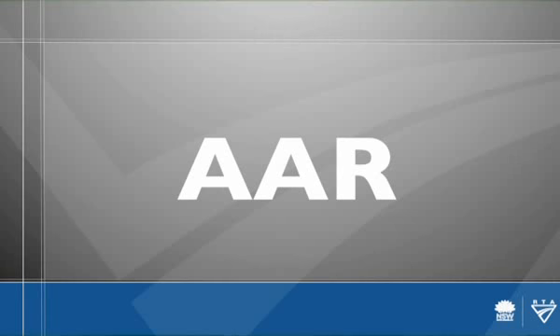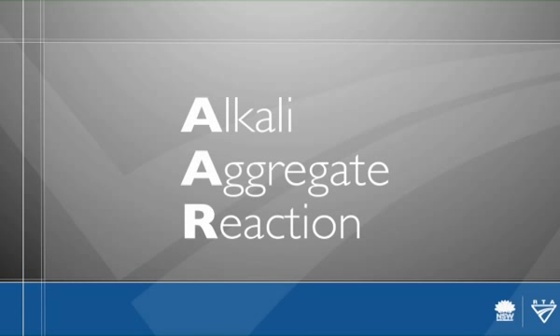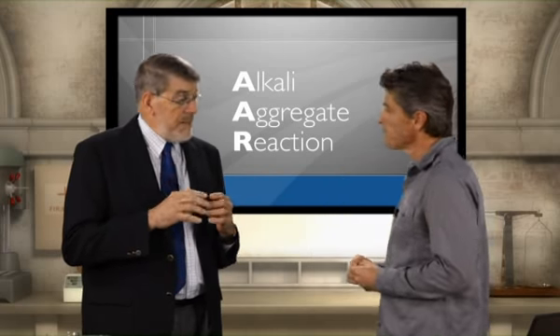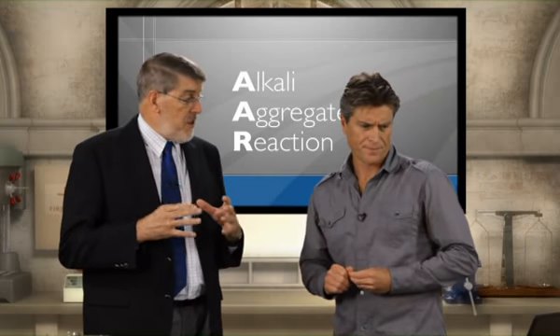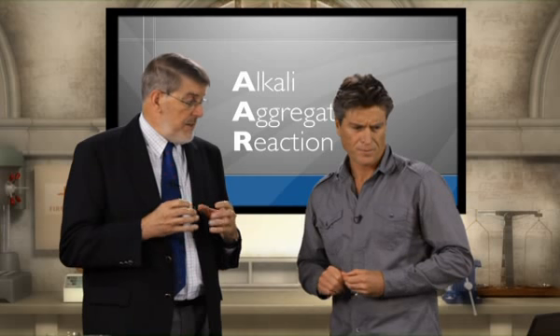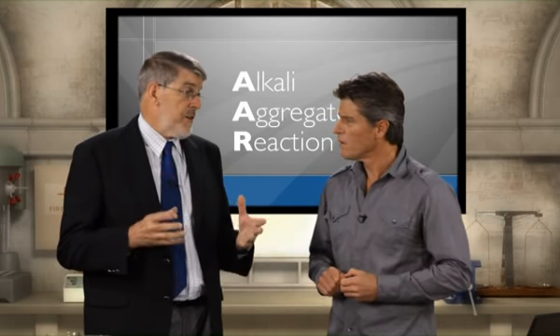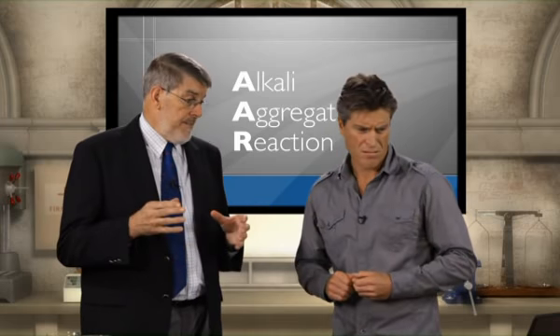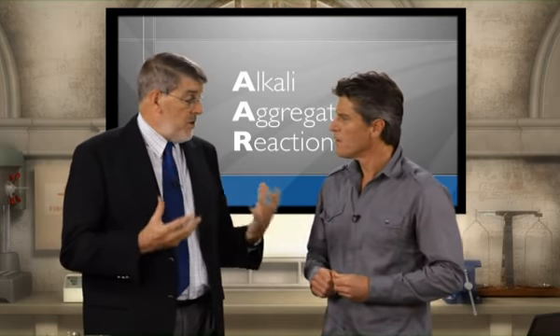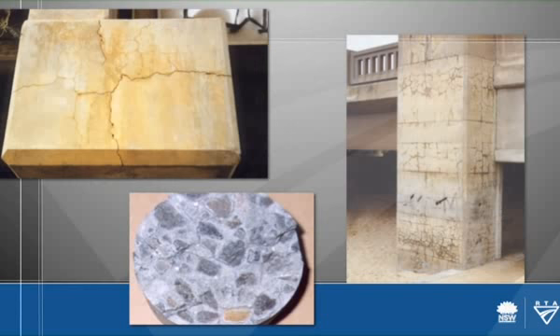Now, AAR, Don, this sounds interesting. Yes, Peter, this is a situation that's arisen in the last few years, and it refers to alkali aggregate reaction. And what happens is, as the concrete strengths have gone up, there's been a reaction between the silica in some aggregates and the alkali in the cement, and it produces a gel around the aggregate as it forms. And this gel is expansive. So over a period of time, and it may be 30 years, this will slowly increase this gel and literally blow the concrete apart, and also will allow the ingress of aggressive agents like chlorides in salt water, etc. And that will further deteriorate the concrete.